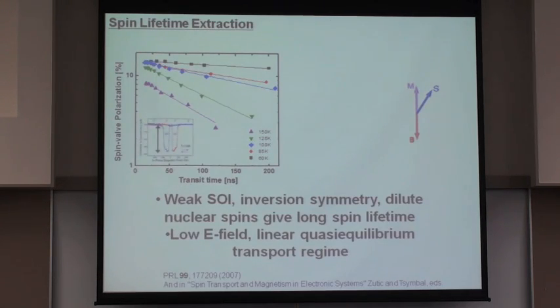So the idea is that we do these spin precession measurements, extract the transit time distributions, and determine the mean of those distributions. Obviously, as I showed you, as you increase the electric field, the transit time goes down. But simultaneously, we also make these spin valve measurements, with which we can determine the spin polarization after transport.